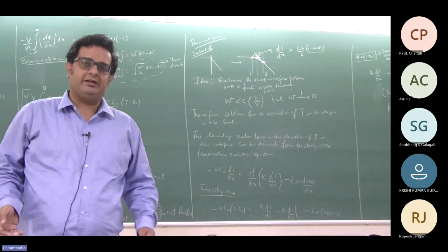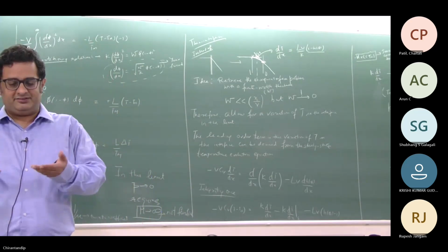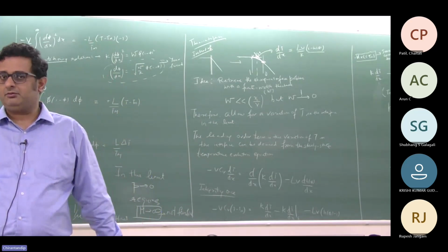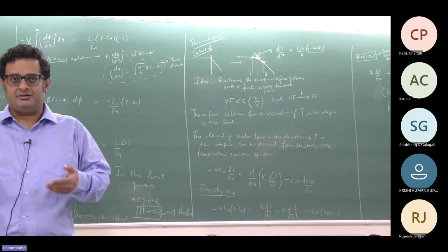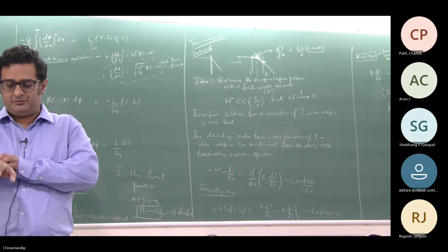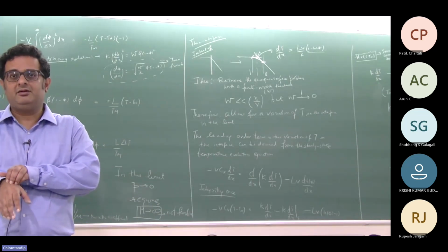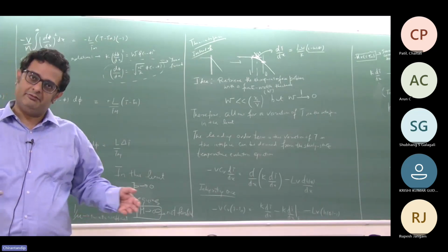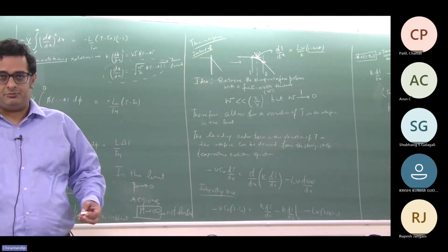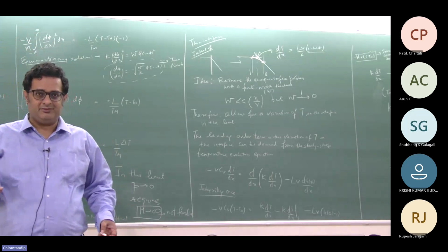So basically, if you are okay with an error of, let's say, 10^-3 in what your solid composition should come out to be, and your interface width is in that range, you're okay with it. But for a person who is not happy with that, you will have to do a correction even for that. So it all depends upon what accuracy of simulation you are ready to settle for.